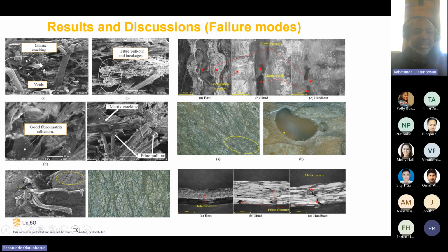Generally, for the tensile properties, the failure mode is characterized by matrix cracking. You could see some voids here as a result of high pressure, and we have visible fiber pullout and breakages. You could see matrix cracking for the flexural here, also a case of fiber pullout here, and you could see voids with this yellow circle. Especially this is the bast under the SEM, which gives us a very good fiber-matrix adhesion. Similar to this figure C. These are the failure modes observed under SEM for the composite using different fiber forms.